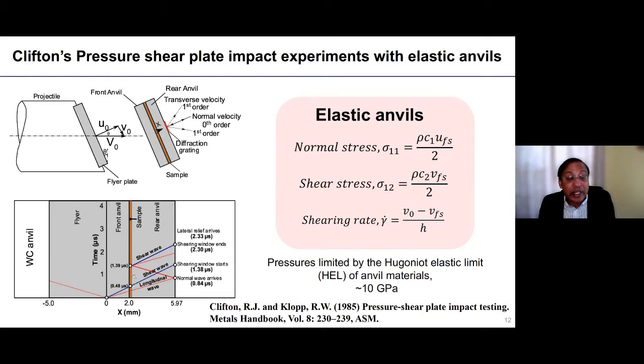And then the shear wave comes and probes the strength of the material. So it is at a nominally high pressure, and this shear wave probes the strength of the material, and the shear wave arrives at the rear surface. In the meantime, the longitudinal wave reflects from the rear surface, arrives back at the interface, and reflects back. When the longitudinal wave arrives back at the sample, it has unloaded the sample because of the reflection from the free surface. Then the event is over. So essentially you have a shearing window from the time the shear wave arrives until the longitudinal wave arrives back. We typically have about a 1 microsecond window.